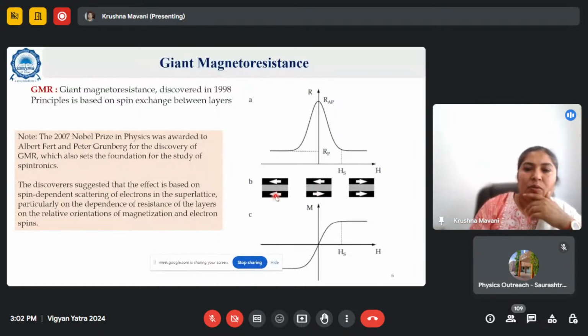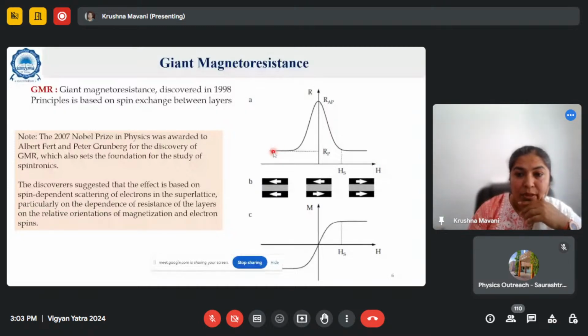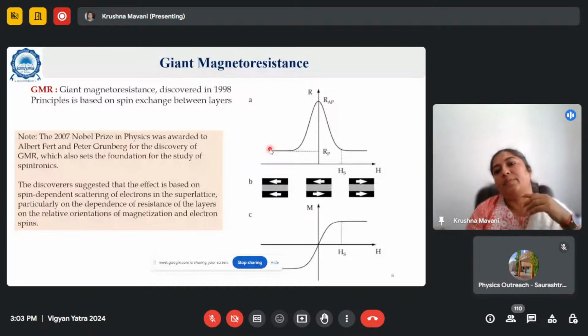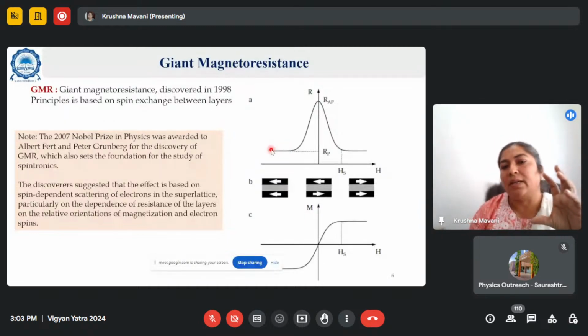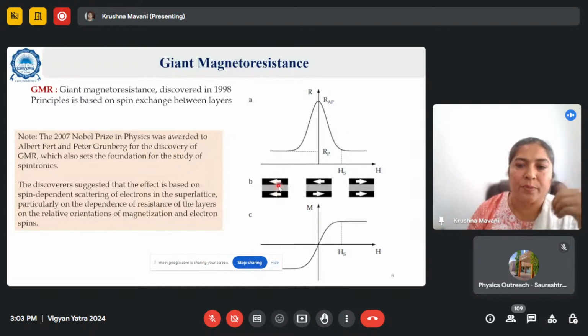But here, basically, this is just to show that in the case of a ferromagnet, if the layers are ideally parallel with each other, what do you see? As you vary the external magnetic field applied to the layers, the resistance value is low. Because it is ferromagnetically aligned, with a spacer layer in between, it is very easy for electrons to tunnel through because they carry the same type of spin. But when these materials are anti-parallel, what happens? They actually